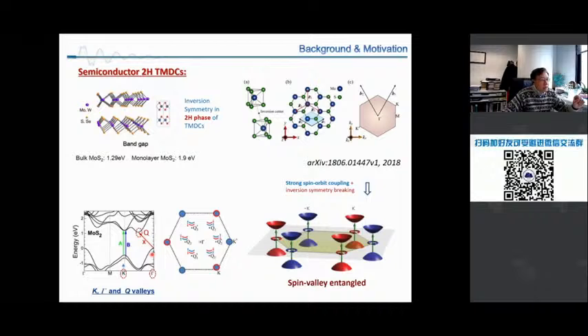the band structure is characterized as a so-called indirect band gap, because if you look at the Q valleys, it's lower than the K valley. But for monolayer, the situation is different. So I listed here the K valley, gamma valley, and Q valley, and that is the topic of today. And I gave you detailed explanations about the transport, about the spin states. The very important thing in this kind of material is the so-called spin-orbit coupling effect.